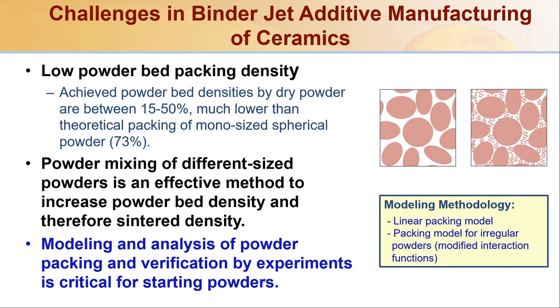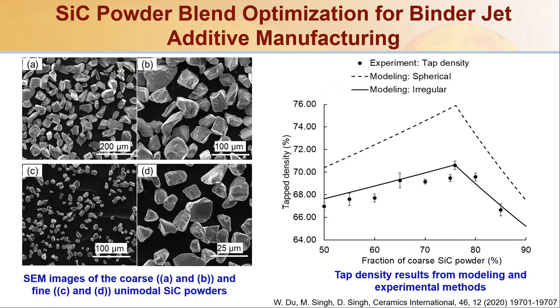So you see on the right side, obviously the idea is, if you have these different particles, large particles, and then you have these small ones, like bimodal or trimodal particles, you can mix them and try to get as high an initial density as possible during the processing. And we used this modeling methodology in terms of the linear packing model. And the other one was the packing model for irregular powders, which is basically by modified interaction functions. So I will not get into a lot of detail about the whole modeling process. Actually, that has been published in a paper which just came out a few months ago.